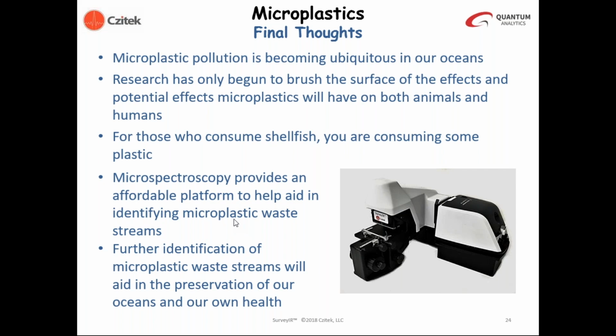Great. We have another question. In your experience, what is the smallest size microplastic that can be analyzed under the different FTIR modes? In our device, the smallest aperture that we use is 60 micrometers. You can analyze samples that are smaller than that, 50 micrometers or less. For the unaided human eye, a good rule of thumb is that the human eye can see materials 100 micrometers and greater. So a 60 micrometer aperture size is less than what humans can observe with the unaided eye.